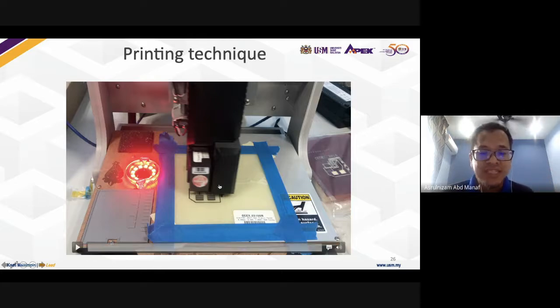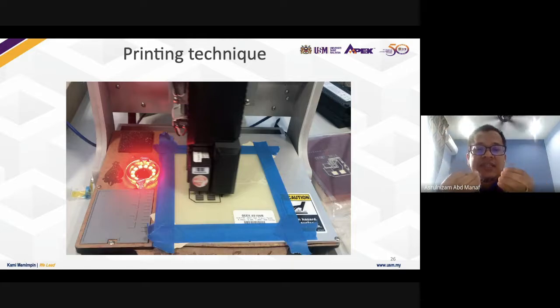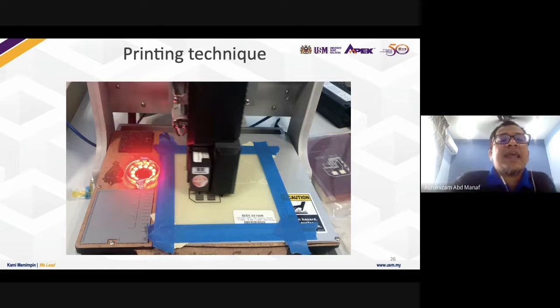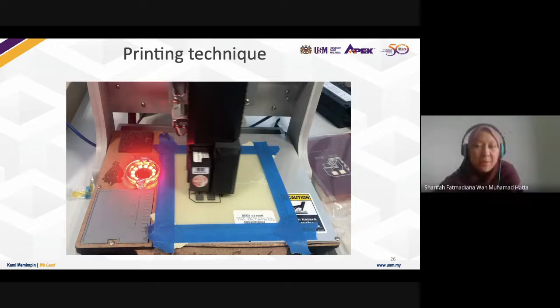And then also the viscosity and also the heater, the cure, because in inkjet the ink is not too viscous. That's why if your cure is too slow, the ink can merge with others. So we face a few problems with cartridge clogging, optimization of the cure temperatures, and also print resolution. Yeah. Okay, thank you, Doctor. If CPE has any problems, I hope you can help. You have very extensive experience in this.